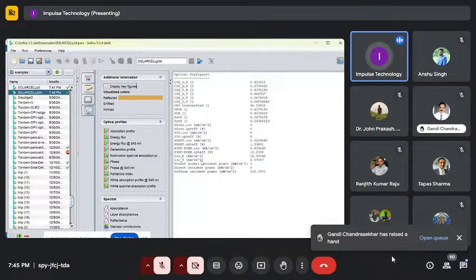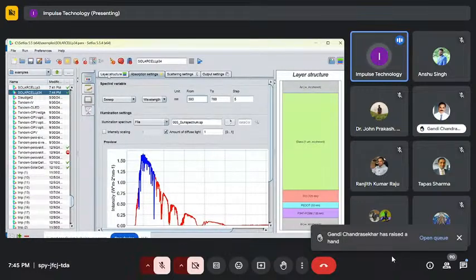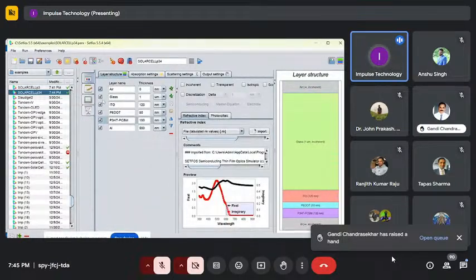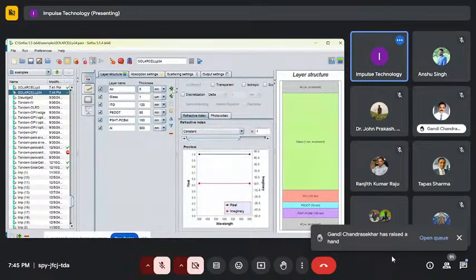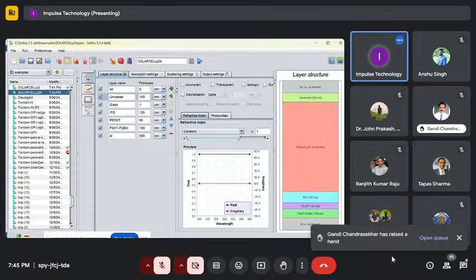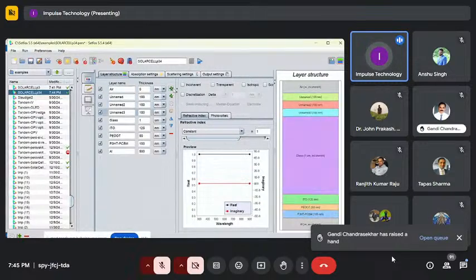And those parameters you can see here. You can see the similar layer structures, and calculate absorption and scattering properties. But if you need solar cells with rough interfaces, you can also go with this. So if you want rough interfaces for the solar cell, you can add the number of layers.